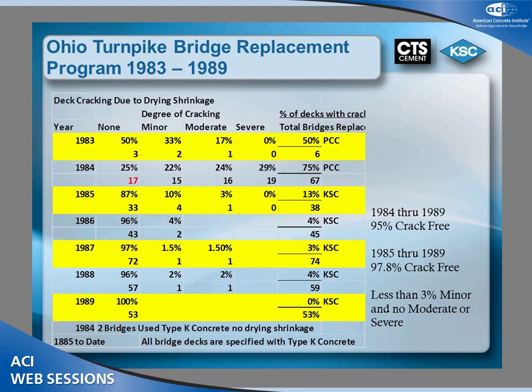But I wanted to show some of the numbers here as far as the number of bridges. If you look over here on the far right, or underneath that, it says 50% Portland cement concrete. There were 6 bridges that were constructed. You see that? And then in 84, there was 67. Those 2 years was Portland cement concrete. From there down, this was all shrinkage compensating decks. You can see 38, 45, 59, and 74 bridges. So there's quite a few bridges.